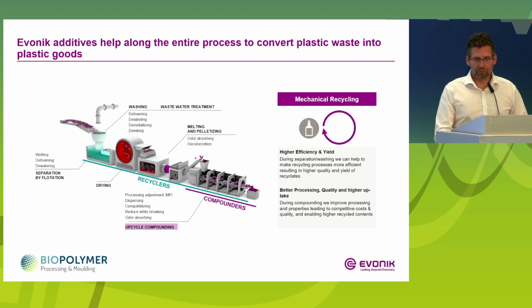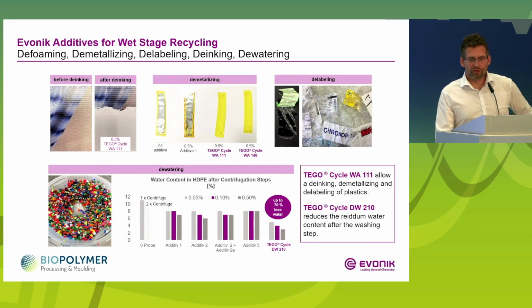And during the washing step, we have additives for so-called de-inking, de-labeling, demetallizing, which we will see in the next slide as an example. And during pelletizing or during compounding, we can incorporate additives for malodor absorption and compatibilization. Yeah, here you can see some examples that ink really can be removed, to have a cleaner recycling stream, and even metallization can be removed, or some labels. And with the dewatering, we have one additive which is also biodegradable, so that we have no wastewater contamination, for example. And then we can reduce the water content to save thermal drying energy.